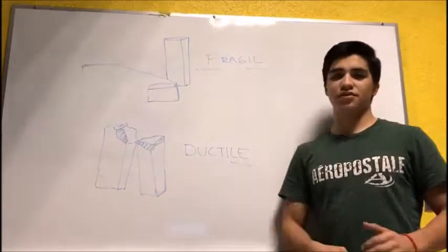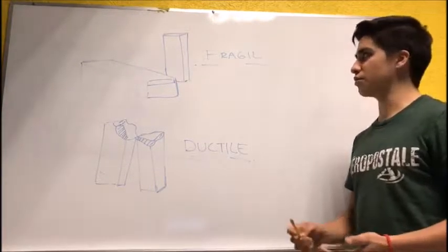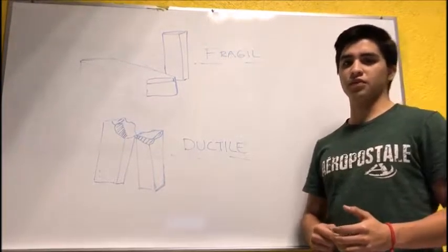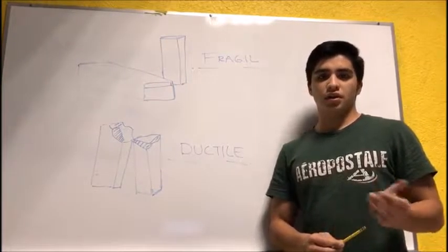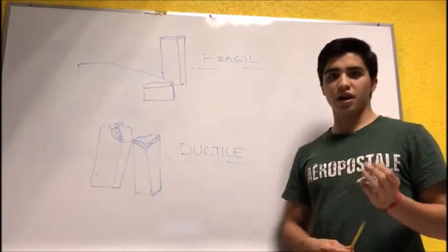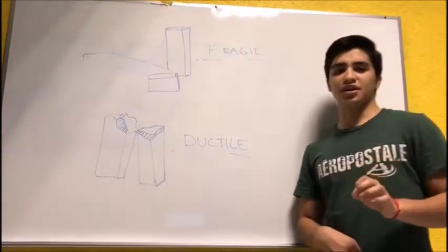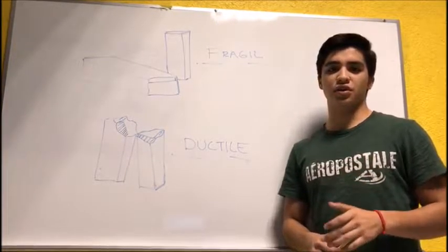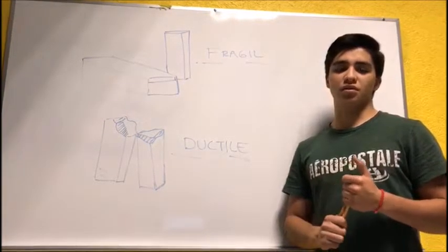On the other hand, we have the brittle fracture. It occurs with little or no gross plastic deformation and takes place along the crystallographic plane. It's for BCC and HCP in this method. It's a fracture of a metal or other material without appreciable prior plastic deformation. It's a break in a brittle piece of metal which fails because stress exceeds cohesion. In brittle fracture, cracks run close to perpendicular to the applied stress.